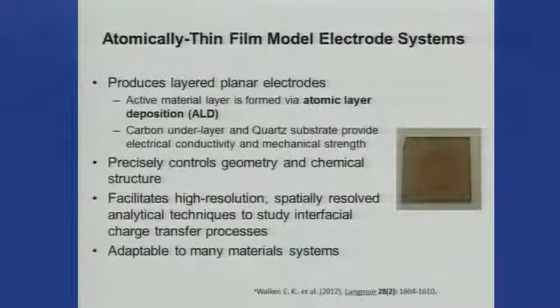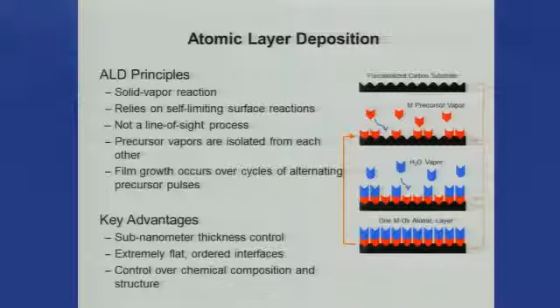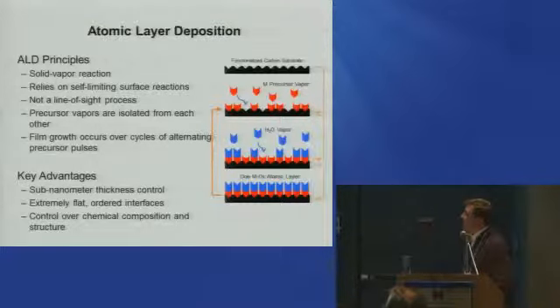So we've gone to this kind of spectroelectrochemical platform where we use optically transparent carbon for a number of reasons. One is that you can make it really flat and it's still conductive. It's also transmissive in the UV, so this allows us to measure the change in the spectral characteristics across a very large window. Of course, we then wanted to make a very well-confined model electrode on this, and Joe talked about using ALD. It's really amazing how well-controlled this process is, where you grow things in a layer-by-layer assembly. There are a lot of advantages: it's not line of sight, so you don't get shadow effects; the precursors are pretty much reactive at room temperature or slightly above, so you don't have other heat-driven factors that change the nucleation and growth behavior; and it's truly one layer at a time, so you get really good control.